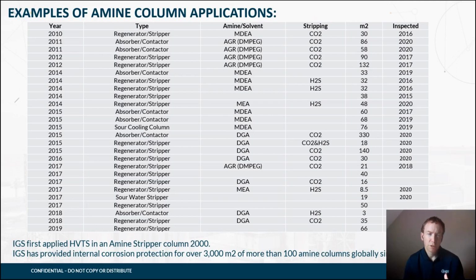Over the last 20 years, IGS has installed these high velocity thermal spray systems in lots of different amine columns, operating with different types of amine in different environments. But the overall result has been the long-term protection of the internal surfaces of these vessels against corrosion and erosion. So since 2000, we've approximately applied around about 3,000 square meters of surface area.